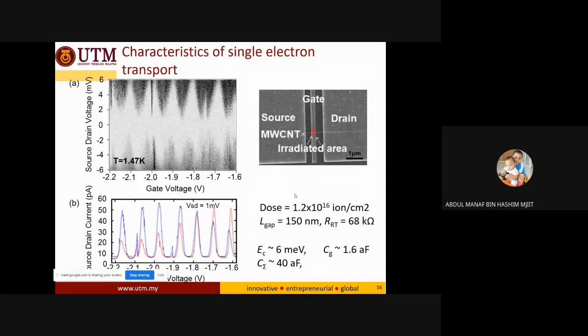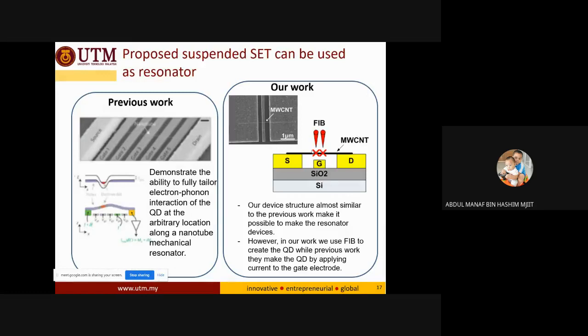Actually, just now I showed you the suspended carbon nanotube on the source and drain, but for the SET I didn't show you the process here. Anyhow, we just add a gate electrode during the fabrication of the source and drain electrodes together. So we have a source, drain, and gate. When we fabricate the source and drain, we also fabricate the gate electrode together, and then we transfer the carbon nanotube onto the source and drain. This means that the gate is located at the bottom side.